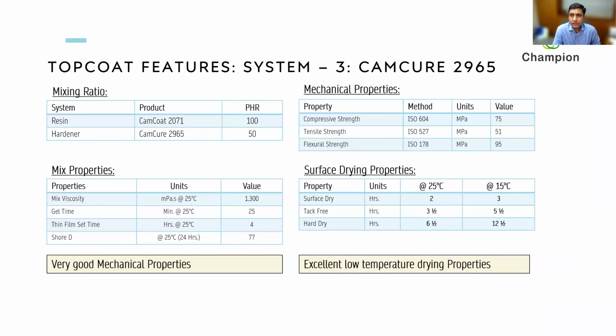The mechanical properties for the system are also very good. The compressive strength, the tensile strength, and the flexural strength are very high. And the surface drying properties we have checked at 25 degrees as well as 15 degrees. And you will notice that even at 15 degrees, the surface dry time is 3 hours, the tack-free time is about 5 to 6 hours, and a hard dry time is about 12 hours, which is very, very convenient even in cold temperatures.